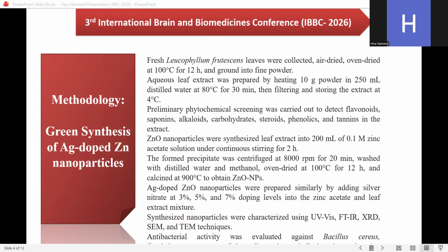I used 10 gram of powder in 250 ml distilled water at 80 degrees centigrade for 30 minutes. Then I filtered it with Whatman filter paper number 1 and stored the extract at 4 degrees centigrade. Then phytochemical screening was carried out to detect flavonoids, saponins, alkaloids, carbohydrates, and other tests.